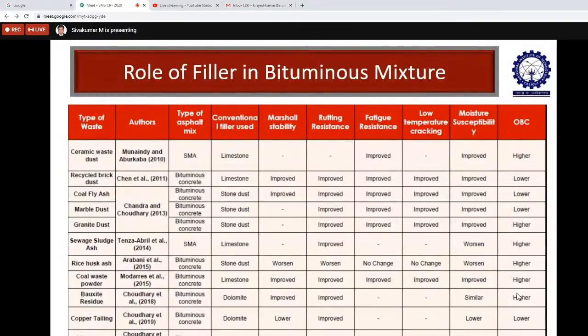For example, alternate materials for the fillers: ceramic waste dust or recycled brick dust, coal fly ash, marble dust, granite dust, sewage sludge ash or rice husk ash, coal waste powder, bauxite residue, copper tailing or limestone sludge. Only some are listed here. All these alternate materials are reused as filler, and they are tested. The research has been done, they are all satisfying, and they improve properties, for example, Marshall stability, rutting resistance, fatigue resistance, low temperature cracking, as well as moisture susceptibility of bituminous mixes, mainly the OBC. The OBC is improved, that means some fillers lower the OBC and some increase the OBC because of the surface area. The references are also given, so later on it can be checked.